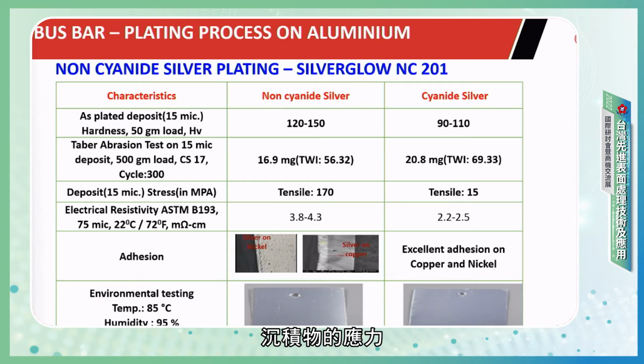Stress of the deposit is much higher compared to cyanide silver. The reason is that the texture of the deposit has a lot of voids compared to cyanide, and under TEM analysis we can see these voids, which eventually trap some impurities, for example hydrogen, carbon, nitrogen, because of the complexes we discussed. From those complexes we get some nitrogen, oxygen, or carbon, and of course from the electrolysis of water we get hydrogen and oxygen.